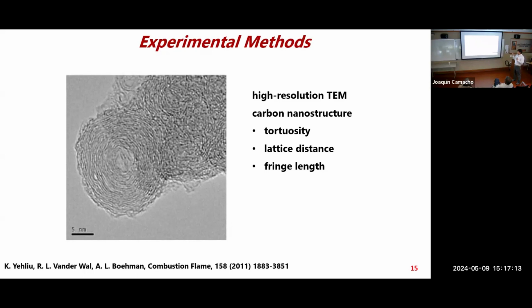For the last decade or so, researchers have been quantifying this in terms of how straight this lattice is, and the distance between this lattice. What's interesting is that, yes, it does help to develop some of the models of soot formation and how these grow in engine conditions. But you have to be very precise, because there's not a lot of variation. This pretty much represents all soot in all typical flame conditions. And what I'll show is the particles I'm forming are drastically different, a completely new regime than typical soot in combustion engine research.